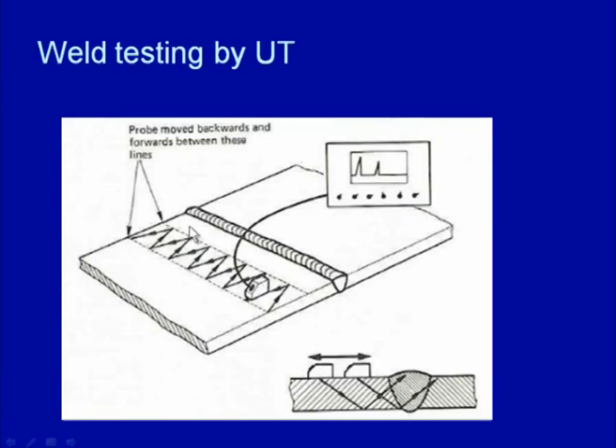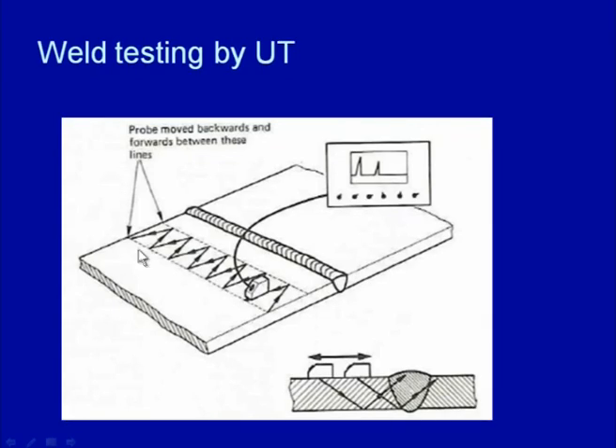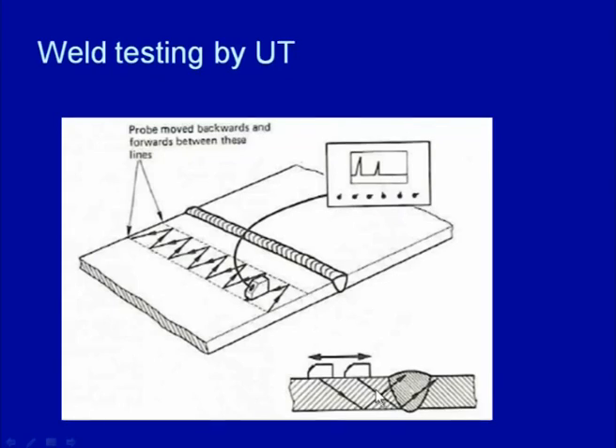So, if we want to scan the complete length of the weld, then two lines are drawn in such a way that the entire width of the weld joint throughout the length is scanned. After drawing these two lines, the probe can be oscillated or moved between these two lines, so that the entire weld length is scanned. Depending upon the type of probe being used, the location of these lines will be set away from the weld zone.